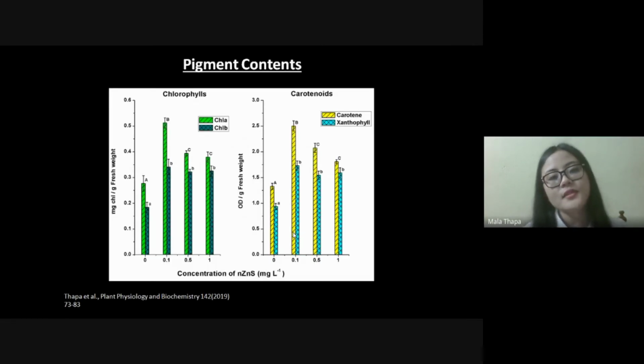Now, photosynthesis is a very sensitive process and its efficiency decreases under stress. To investigate the effect of zinc sulfide nanoparticle on photosynthesis, we measured pigment content and found that treatment of zinc sulfide nanoparticle significantly increased pigments in mungbean plant.